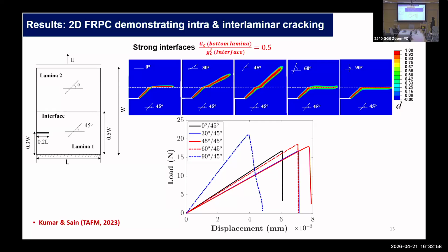But when the fiber orientation on the top fiber becomes 60 degree, it doesn't go to the 60 degree orientation. It just follows the lamination. Okay. And of course, the corresponding behavior is pictured in the load displacement plot also. As you can see, the 45 degree has the most ductile response in terms of the failure displacement being the highest.